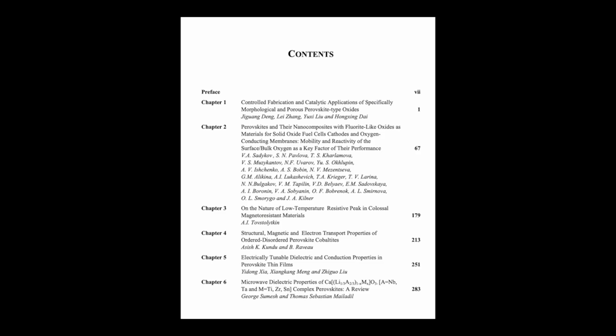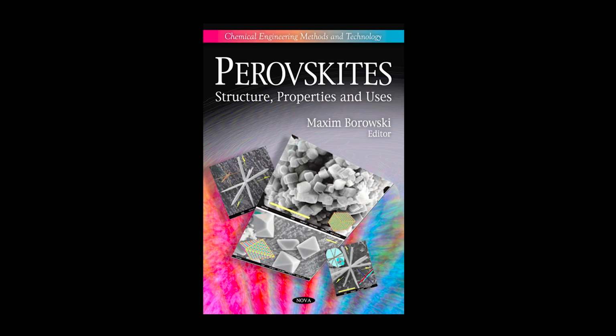we saw research showing that perovskites are even being developed and used as simple ceramic pigments for color. Yeah, this really speaks to their superb thermal and chemical stability. Certain perovskite structures, specifically those based on trivalent cations like A3+B3+O3, are proving to be excellent bases for new, highly stable, and often vividly colored ceramic pigments, especially in the red and orange range. Key examples include the lanthanide ferrites, like YFeO3 or GdFeO3, often reddish-brown, and the chromium-doped lanthanum aluminates, LaAl1-xCrxO3, which can give intense reds.